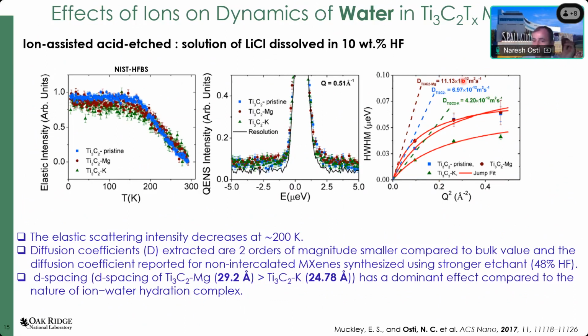So if it makes a very tight hydration shell, we would expect a lower diffusion coefficient, but that is not the case. After getting this value, we went back and checked the d-spacing of those samples, and the d-spacing of the magnesium intercalated MXene is higher compared to the potassium intercalated MXene. Because of that higher d-spacing, water has more freedom to move within that sample compared to the potassium intercalated MXene. That's why we got the higher diffusivity in magnesium intercalated MXene.